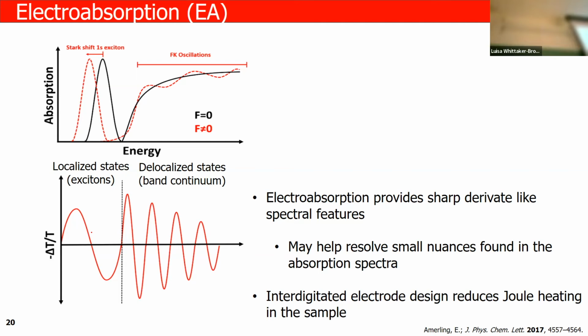Okay, so if you have any defects that are bleeding into the band gap, you will get that sort of information. So the way that we have to do this experiment, because we are now applying an electric field, okay? And it's pretty high, so it's actually 100 volts. And I'm like, all right, so this is high, but it's actually AC. So it's not that big of a deal, it's still high.